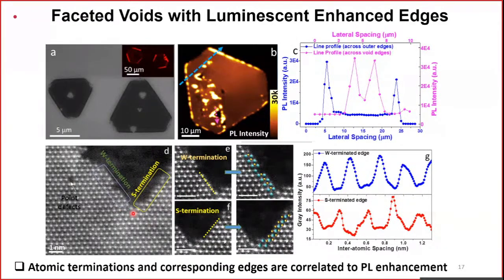Again, we looked at the termination by looking at the HAADF imaging more closely: tungsten termination, sulfur termination, and so on. And we are also able to look at PL mapping, clearly correlating with the termination. And again, oxygen we are not able to clearly capture in the imaging, but we do get the signal of oxygen when there are papers talking about WS2-x. Some sulfur is replaced with the oxygen. They call it oxysulfide and so on. Very, very small amount, but we can clearly see the enhancement in the PL signals.